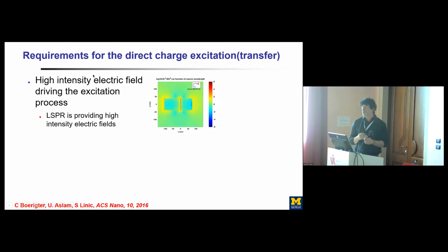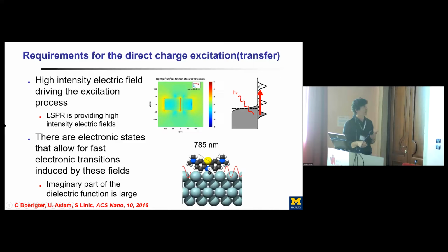So we performed these studies for a large number of organic dye molecules, and we came up with a simple set of rules that tell us about when this direct charge transfer takes place. So you need to have high intensity fields that are driving this excitation process, and localized surface plasmon resonance is giving you that. And then you have to have electronic states that are available for that energy to go through that molecule, or through that interface of the molecule and nanoparticle.